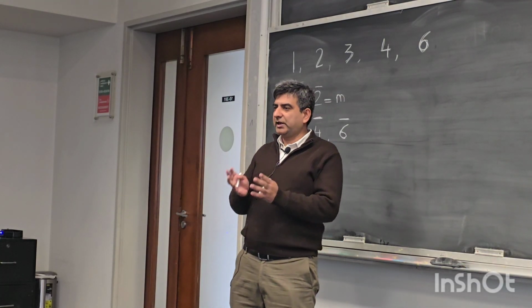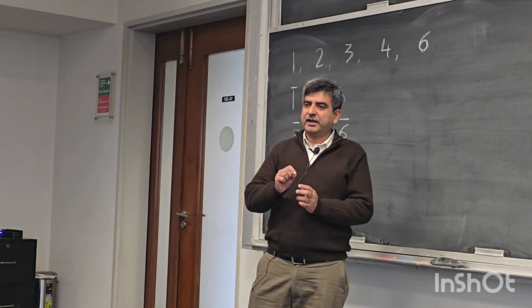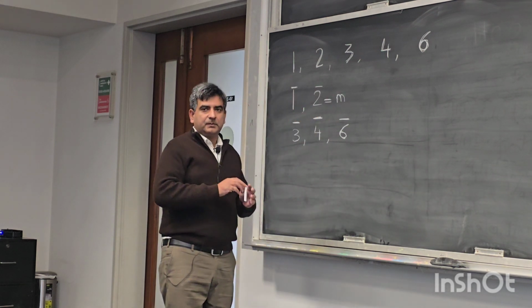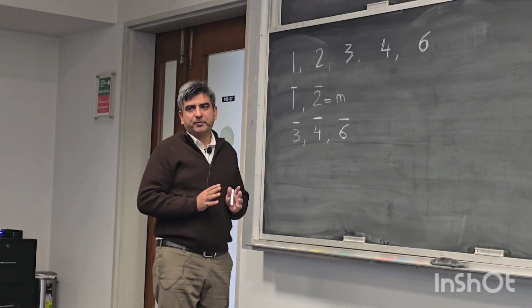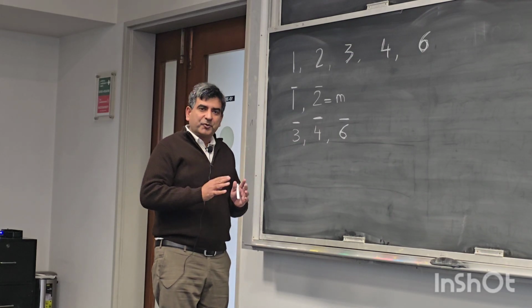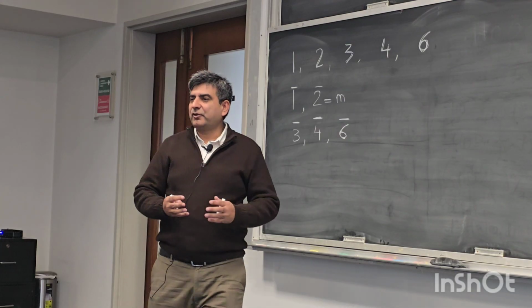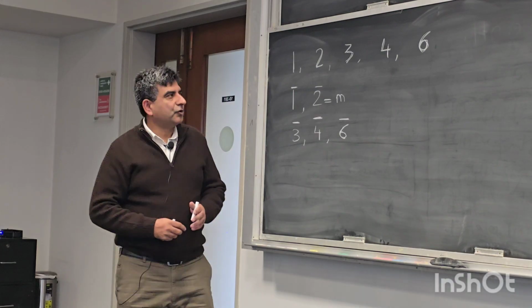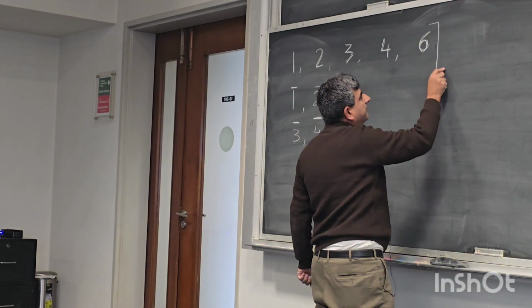How does the crystal look from the outside? If you take the geometric center of that crystal and perform a group of point operations corresponding to the point group to which that crystal belongs, the external morphology of the crystal will remain unchanged. So these are the 10 point operations, and they all come in combinations.